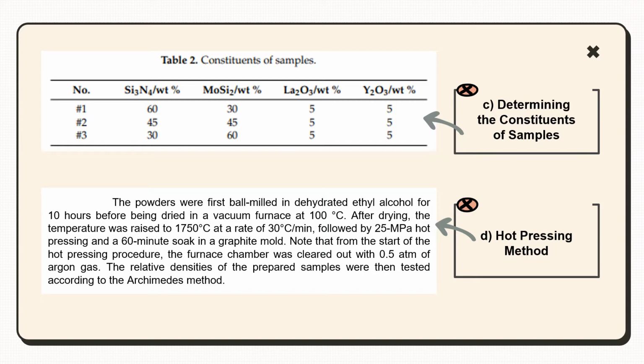Finally, sample number 3 is constituted of 30% of silicon nitride, 60% of molybdenum silicide, and 5% each for lanthanum oxide and yttrium oxide. Now for the hot pressing method, the powders were first ball milled in dehydrated ethyl alcohol for 10 hours before being dried in a vacuum furnace at 100 degrees Celsius.